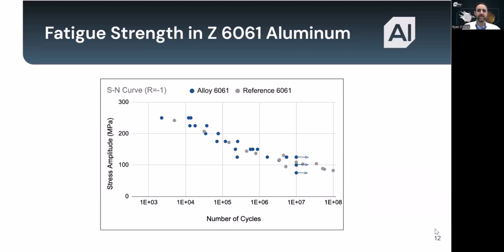So we talked about tensile strength and ductility, but for many defense applications, fatigue strength is just as important. Components in aircraft, UAVs, and munitions don't fail in a single load. They're subjected to millions of cycles over their service life. This chart shows the fatigue performance of our Stack Forge 6061 aluminum compared against reference data for wrought 6061. What you can see is our material follows the same S-N curve behavior as conventionally processed aluminum, with no unexpected knockdowns or brittle failures. Again, in practical terms, this means that Alloy's aluminum can survive the high-cycle environments defense platforms face: vibration in aircraft, oscillating thermal loads in a directed energy system, or repeated pressure fluctuations in liquid cooling hardware.